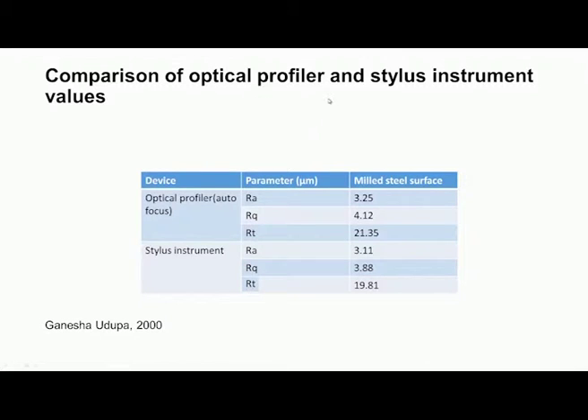So, you can see here the comparison of optical profiler and stylus instrument values. These are the results obtained by the optical profiler. Okay, this is for a particular milled steel surface. Ra value was 3.25 micrometer, Rq value was 4.12 micrometer, and Rt is 21.35. The same surface was checked using a stylus instrument. You can see here the Ra value is almost the same, 3.2 here and 3.11 with the stylus instrument, and Rt value was 21, and here it is 19.81. So, like this we can always compare the different systems and check how they behave.